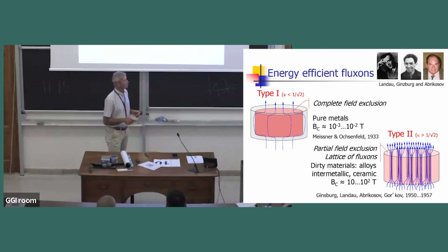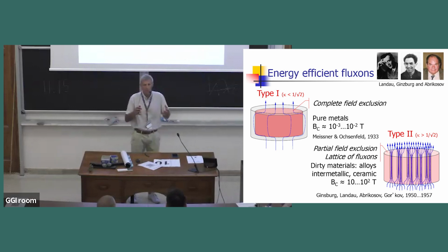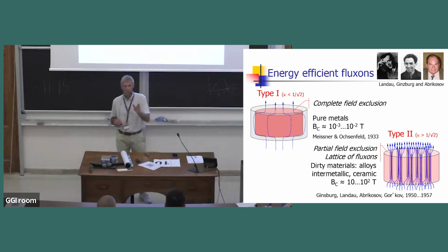But there are other ways. Instead of pure metals, which have a critical field, the maximum field that they can expel, of the order of millitesla, or tens up to 100 millitesla for niobium. By the way, that's why niobium enters in cavities.